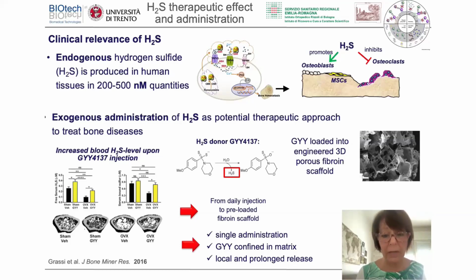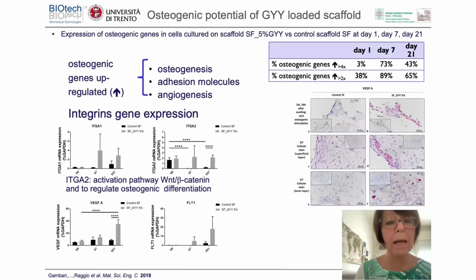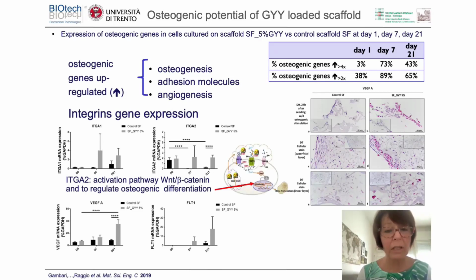Despite this short release time, we performed in vitro tests by culturing human mesenchymal stem cells in dynamic condition up to 3 weeks. As you can see from these images, from this scheme, the presence of the GYY was able to improve the expression of osteogenic genes for 3 weeks, not just for 12 hours, and the production of angiogenetic factors was also activated and increased over time. So what was interesting to observe is that the 12-hour release of the GYY, the sulfur donor, was enough to trigger this mechanism based on the beta-catenin.